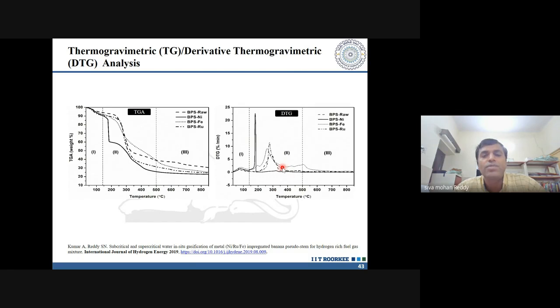And we see that specifically for iron, you have a peak above 400 degrees centigrade, which says that the ring components like lignin are going to be effectively cleaved in the presence of iron compared to the other two materials. And furthermore, if you see that the presence of your metals has resulted in higher peaks compared to the raw peaks, so now what does that mean?